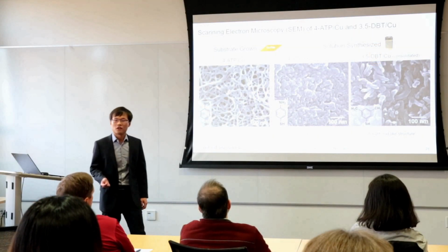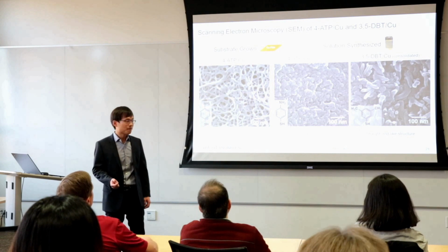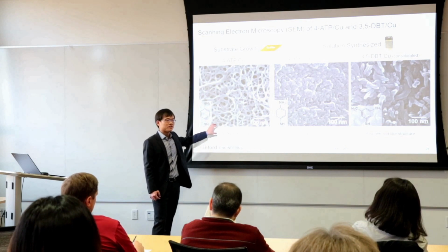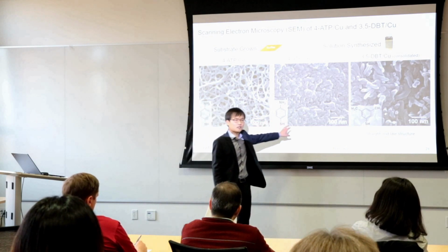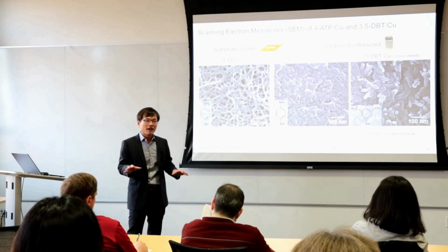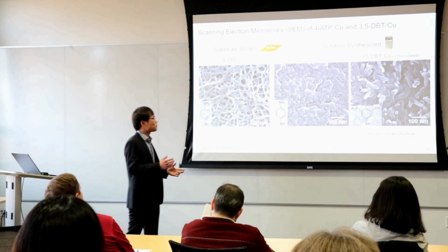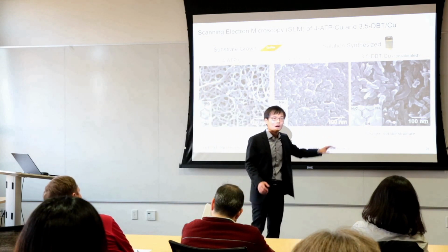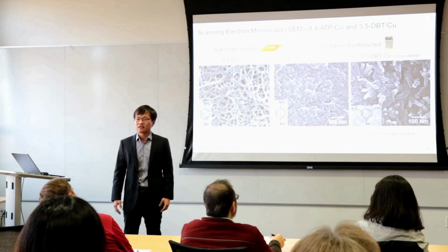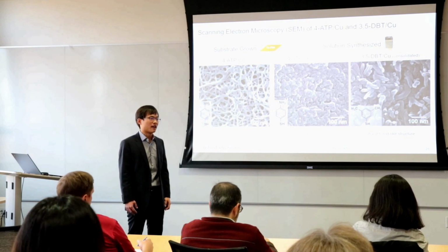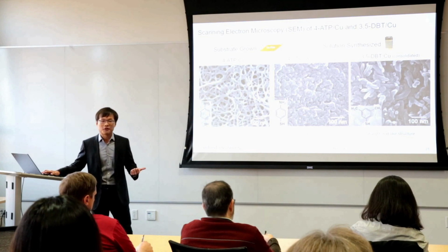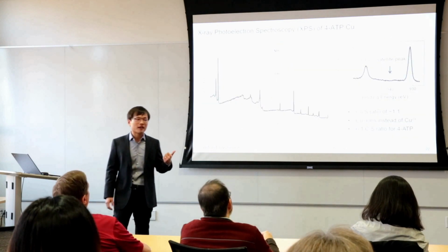And in terms of the morphology for each benzene thiol molecule that we have used, the 4-ATP copper, regardless of how it is synthesized, whether substrate grown or solution synthesized, always had a lot of branches. In contrast, the morphology formed by 3,5-DBT copper is very straight, rod-like material. Keep this morphology in mind as we will refer back to it later as we look at other results. Now we know the morphology of our nanowires. What about their chemical composition?